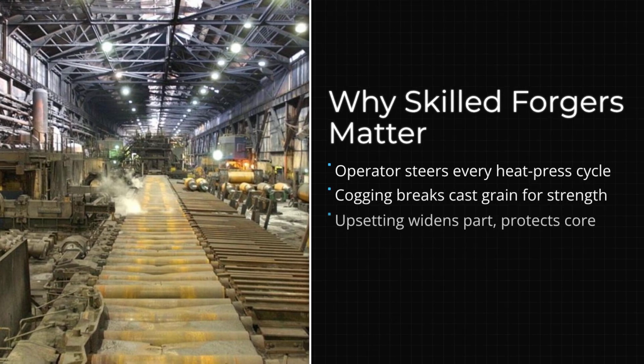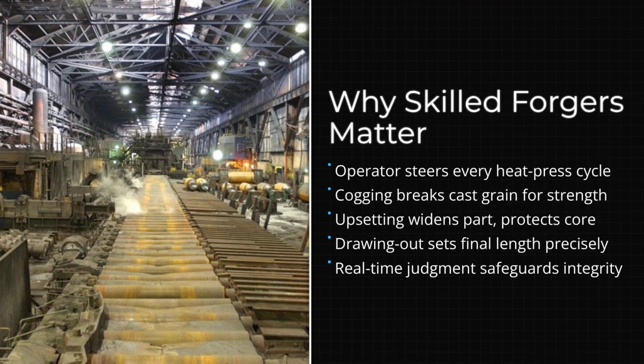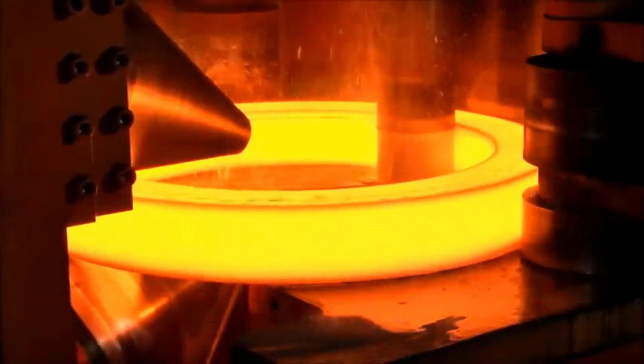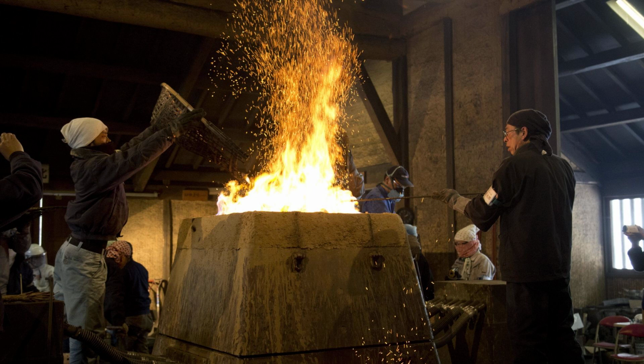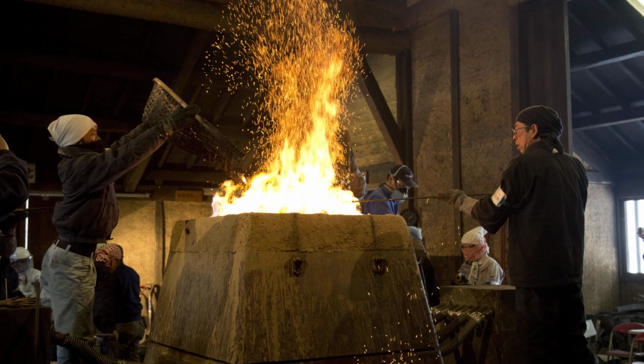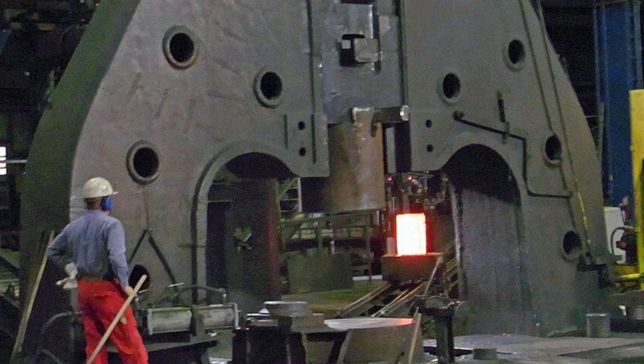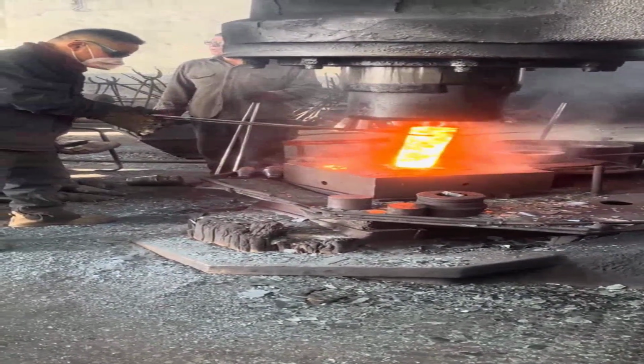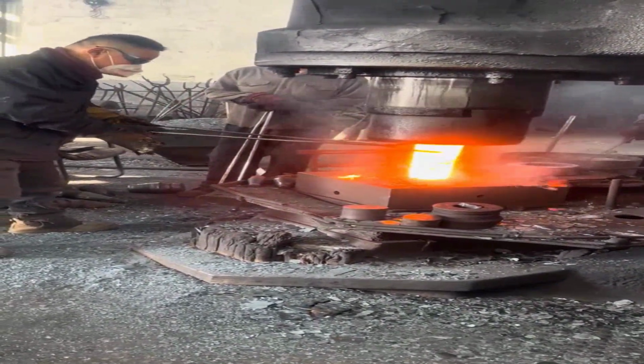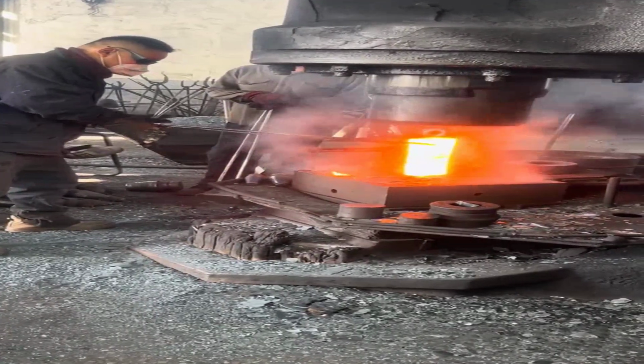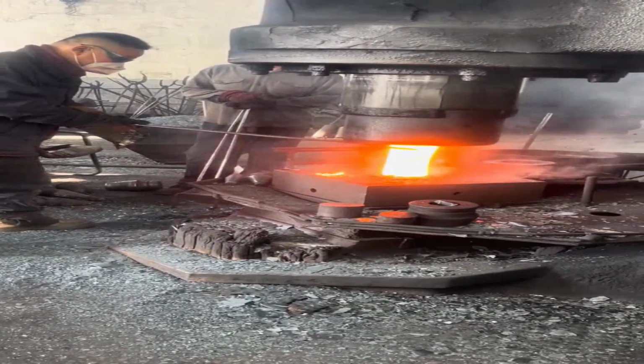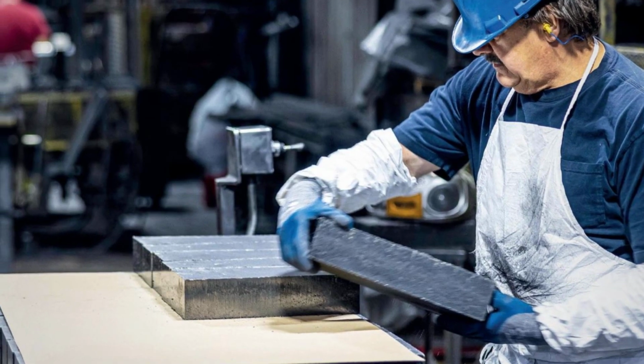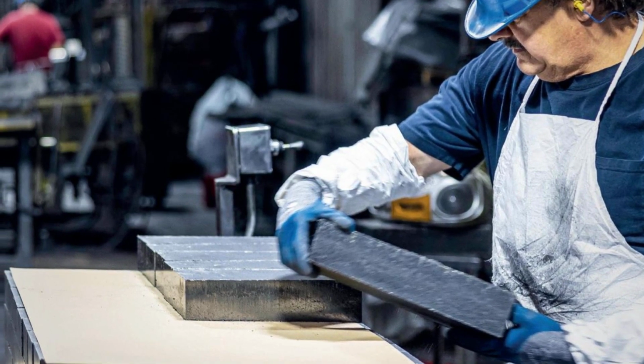The forging sequence includes cogging to break down cast structure, upsetting to reduce height while increasing diameter, drawing out to lengthen the piece, and ring rolling to form hollow rings. A single major component may require 2 to 4 months of repeated heating and pressing cycles, and this is where automation fails completely. Open die forging requires continuous repositioning of the workpiece between press strokes, real-time adjustment of direction and angle, and constant decisions about where to apply the next deformation.